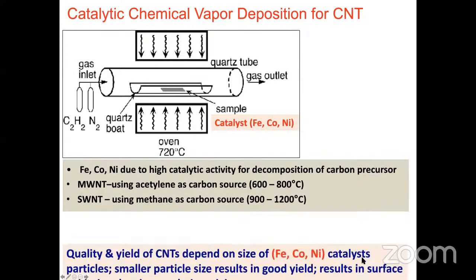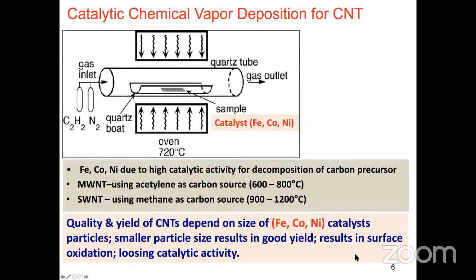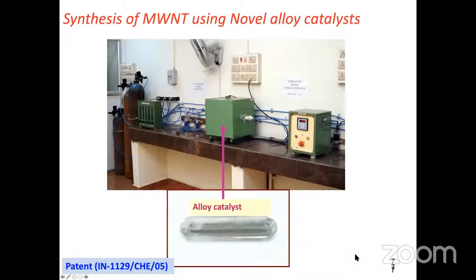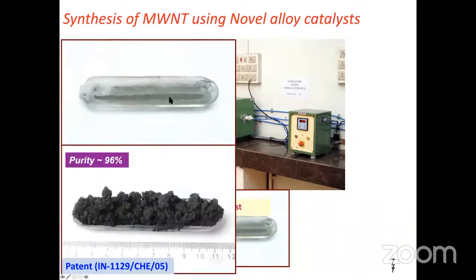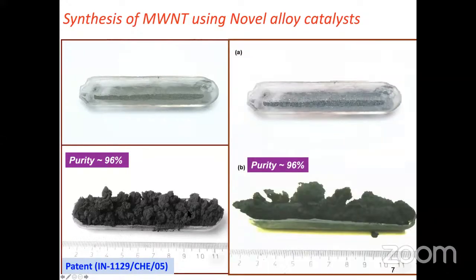Okay, so you can see the furnace where we have the quartz boat. Inside you have the quartz tube, different gases, and this is a catalyst. Before and after the experiment, you can see a black kind of powder, and if you take the high resolution microscope images, you can see that they are the multi-walled nanotubes.